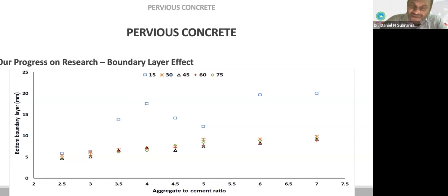Now, I did not talk about the compaction in the earlier ones. Compaction is also supposed to be around 30 blows with a standard Proctor rammer, which actually gives a uniform property. So you can attain a little bit more uniform porous concrete mixture with 30 blows of compaction, and it doesn't reduce the porosity either.